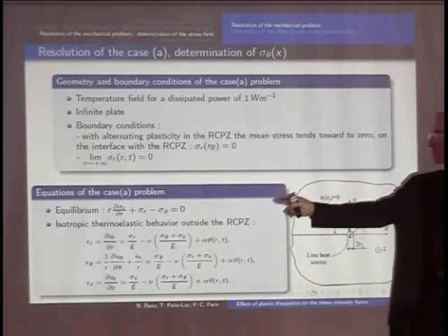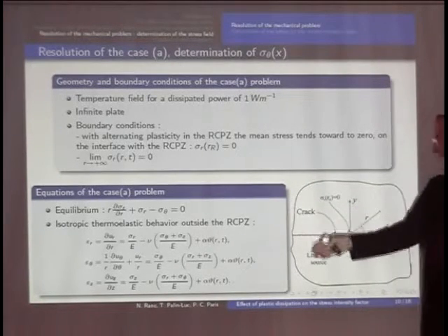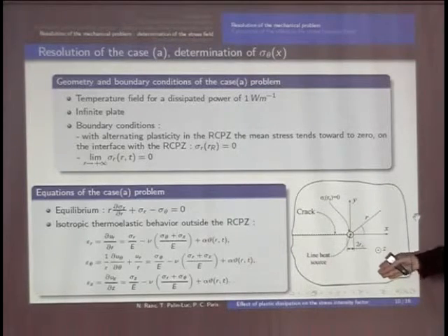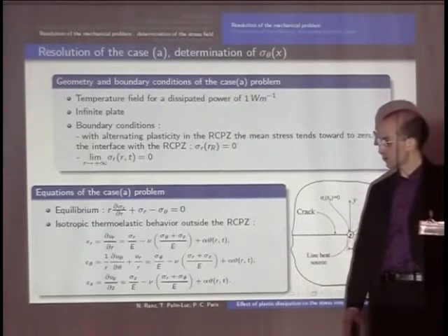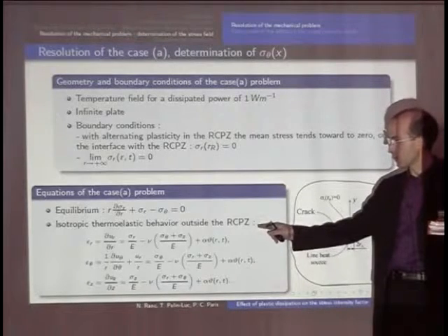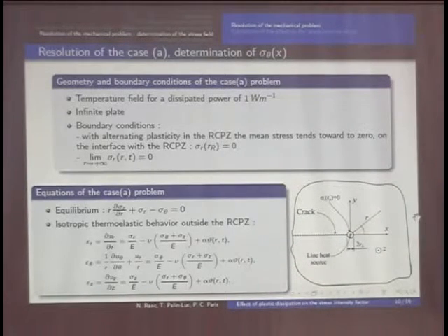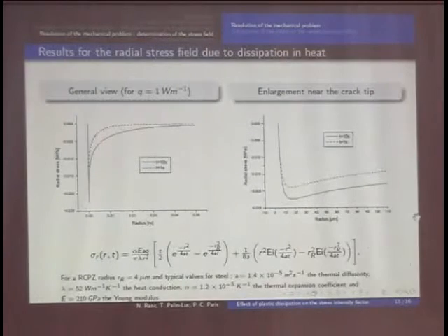And then we write the equilibrium equation. In this case, it's an axisymmetric problem, so there is only this scalar equation, and outside the reverse cyclic plastic zone, thermoelasticity with isotropic behavior. And we obtain the following results. The first, the radial stress. In fact, it's not important for the effect on the stress intensity factor because the radial stress does not open the crack. The next slide will be about the sigma theta, the circumferential stress.